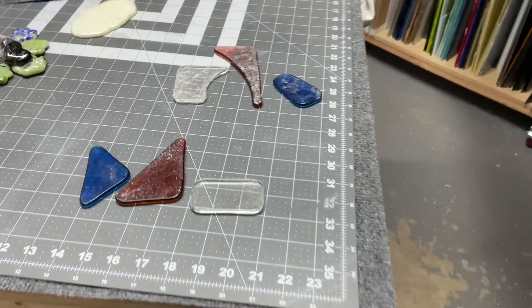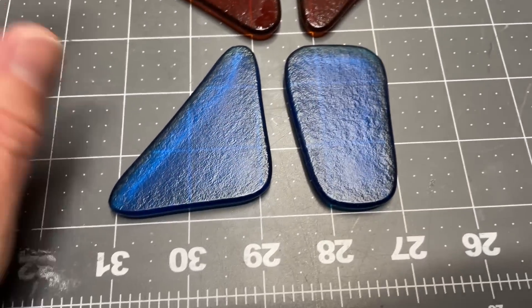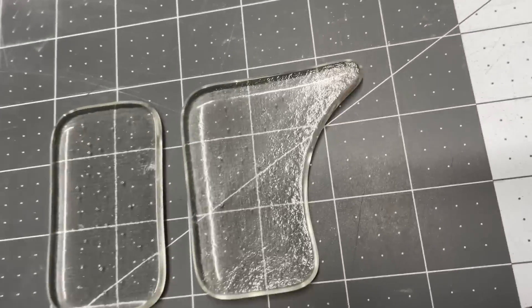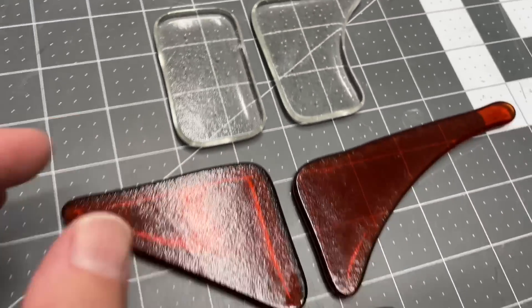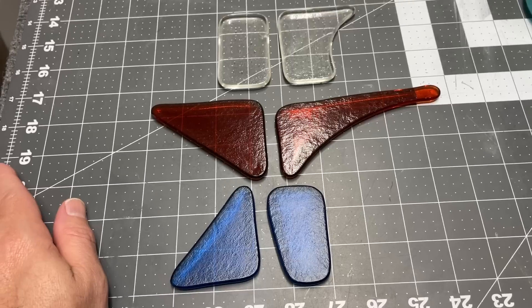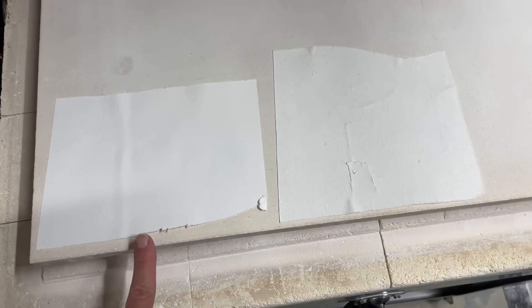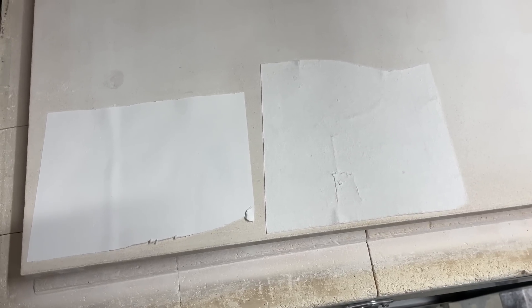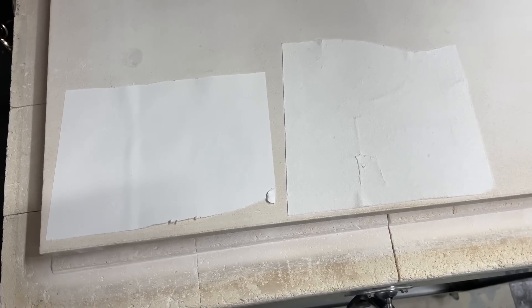Here they are cleaned up — I really don't tell much of a difference between them to be honest. They both clean up well. Held up to the light, I don't see any embedded fibers as had been rumored or complained about. As samples, they look generally the same. After three firings on clear, they seem to be performing at about parity in terms of the end result. The paper clearly looks different and I still believe the old formula will last longer, but so far — while I'm still frustrated that the formula changed without notice — the results seem pretty close to the same.